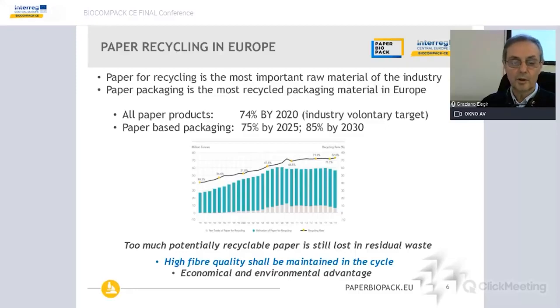increased constantly starting from the 90s, and it's now in 2019 up to 72%. So not yet at the target that was set by the paper industry, but almost there. Why is it so difficult to reach this target? It is so difficult for different reasons, actually. First of all, because too much potential recycled paper is still lost in residual waste. But that's not the only reason.